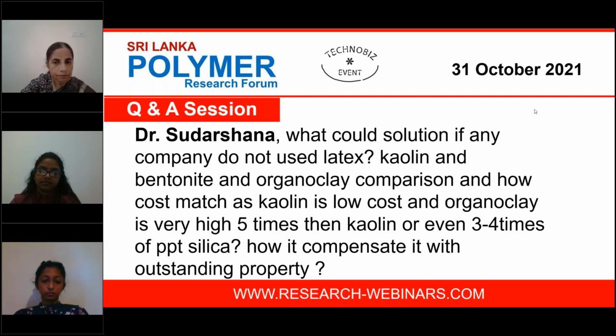Yes, I know that, but normally kaolin is not recommended because separation of the clay is very difficult. I recommend montmorillonite, but you must prepare organoclay from MMT and graft that organoclay. Then clay separation is very easy. Otherwise, we have to separate clay from the clay stack, and then you cannot get the proper result. Normally, the clay we take should have very few aggregated structures.